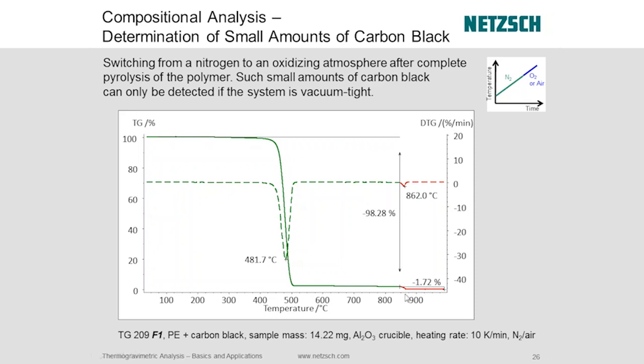But in order to get the carbon black content, we do that by switching, at about 850 degrees, to air or oxygen. And that lets us combust the carbon black. And this is a really important comment here. I mentioned already about the importance of vacuum tight. Remember I said we want to keep outside gases out.